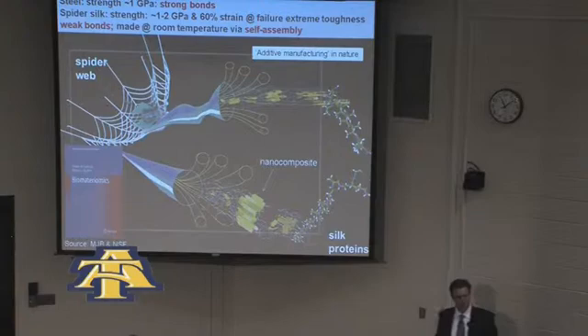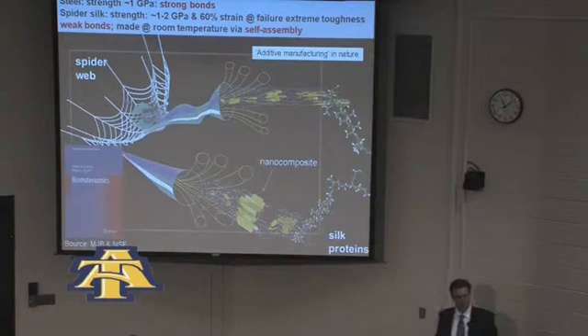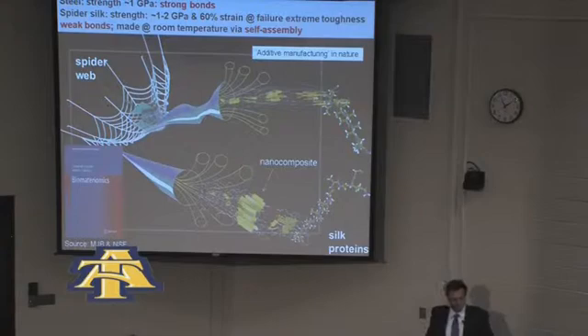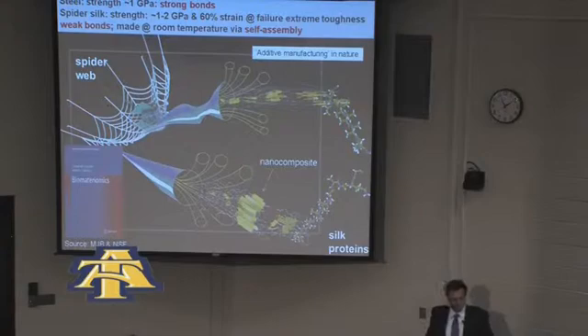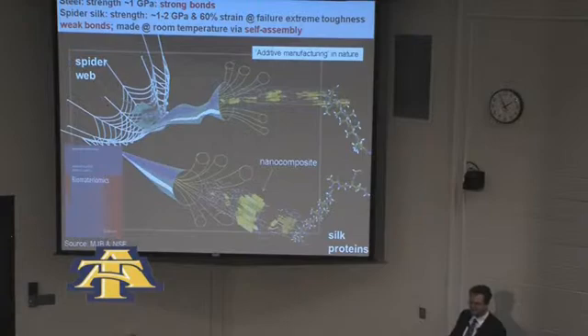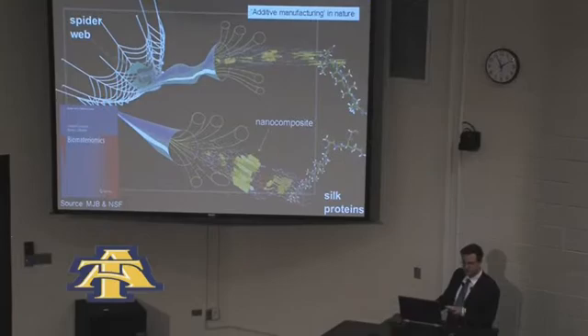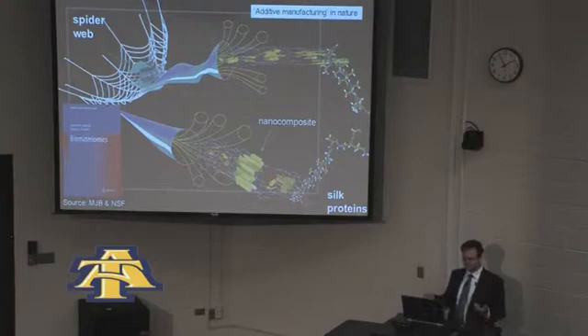If you're an engineer, you might admire the beauty of webs, but what you really care about are the numbers. You go into the lab and test silk — you take a tensile test machine, pull a piece of material, divide the force needed to break it by the cross-sectional area. For silk, the strength is on the order of a gigapascal — the same strength you find in steel, a human-made engineered material created using a lot of energy.